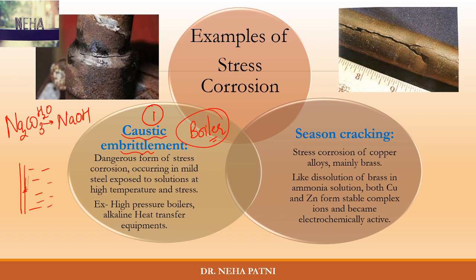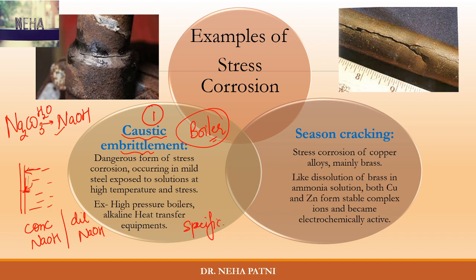When you're heating water in a boiler, if there is a crack in a particular area or the area is under stress, the NaOH makes the water alkaline. In some areas the alkalinity becomes more concentrated NaOH, while in the rest it remains dilute NaOH. When there is a crack and NaOH particles enter, water immediately evaporates and that area has concentrated NaOH while the surrounding area has dilute NaOH. Stress corrosion occurs at the area under stress — the specific condition — and the corrosive environment is the caustic — the selective condition. Iron reacts with NaOH and that is caustic embrittlement. It's a type of concentration cell corrosion.